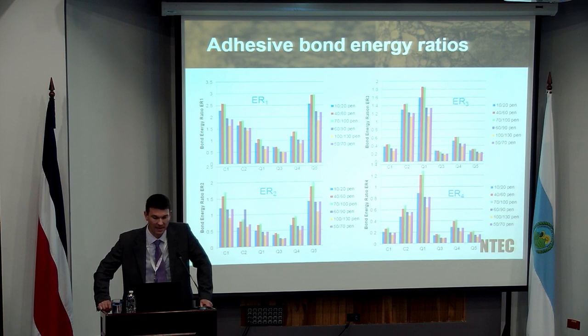There are differences, obviously. If you look at the top right-hand corner, those ratios change slightly depending, again, on whether we're using ER1 or ER2. And at the bottom two graphs, the effect of specific surface area, in other words, how much area is available to bond with the bitumen, now starts playing a big difference. So you'll see differences, again, between those graphs, simply as a function of how much surface area we've got for our particular aggregates. And we know that some aggregates tend to have much higher surface areas than others, depending on how they are produced in terms of the quarrying process and the crushing processes. So those are important factors.